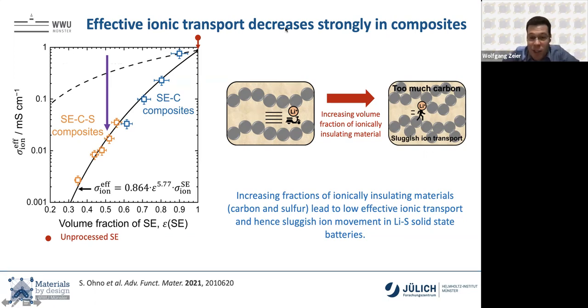So the ionic conductors for sodium, they're much faster. Even though sodium is bigger, it's just much faster in the solid state. So one would think you can actually make 40 millisiemens. So one would think if we translate that to sodium, this would be better. The problem that we have is that all these sodium materials are much more unstable against sodium metal. These lithium materials decompose against lithium, but they form a passivating interface. Against sodium, they form an interface that just keeps growing and runs through the whole battery.